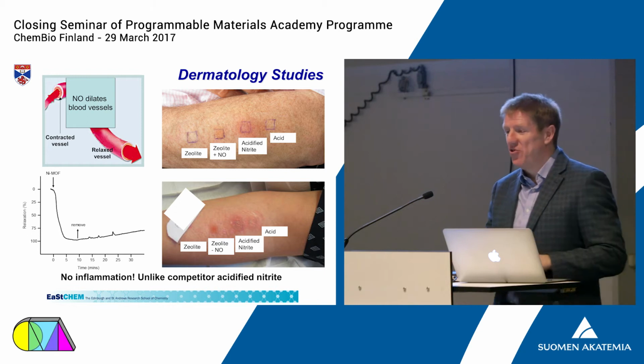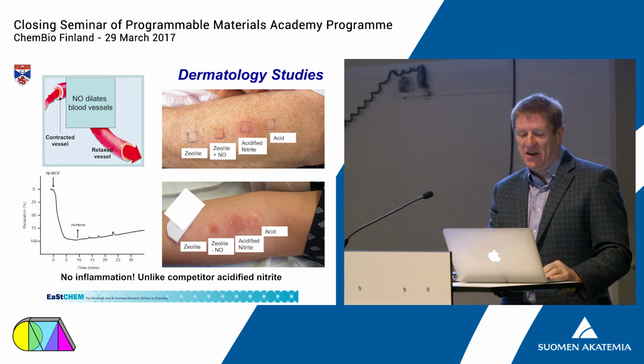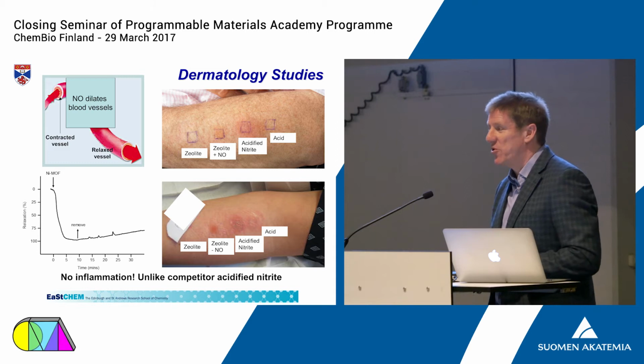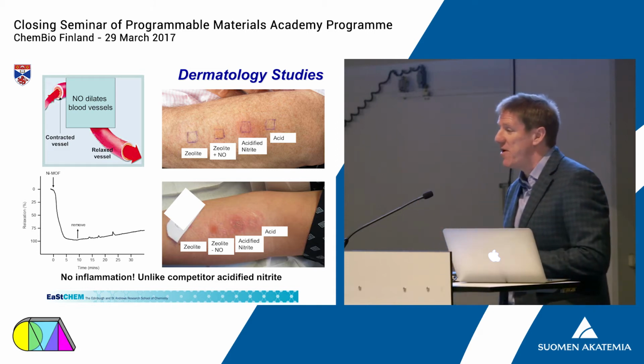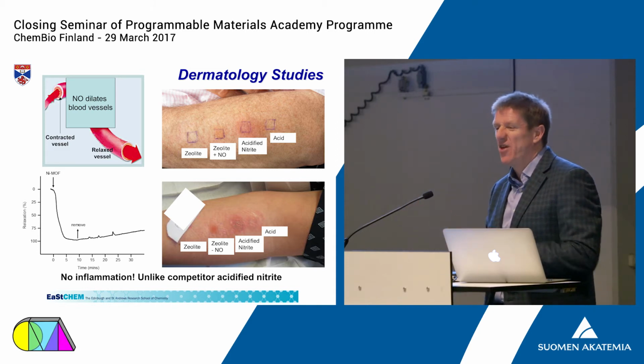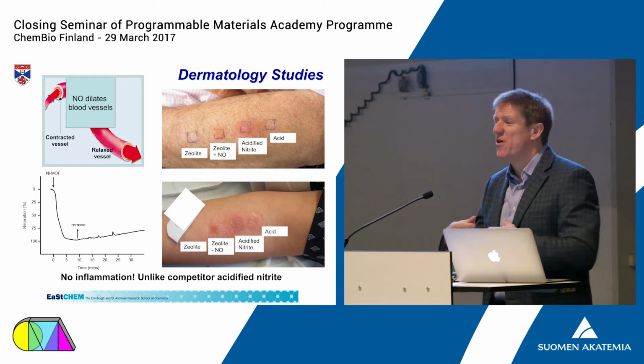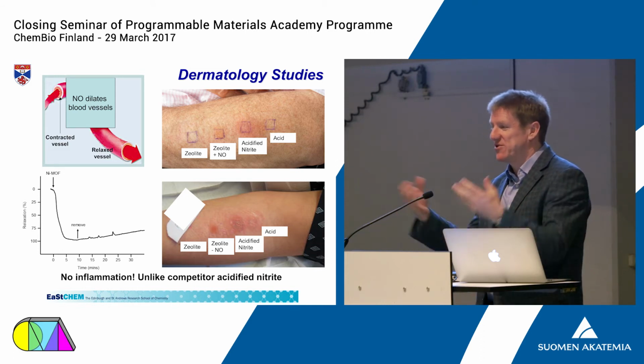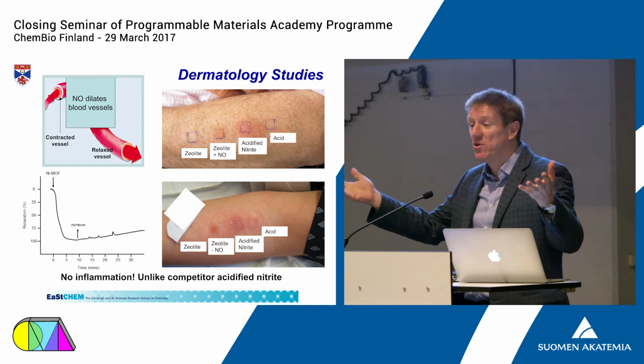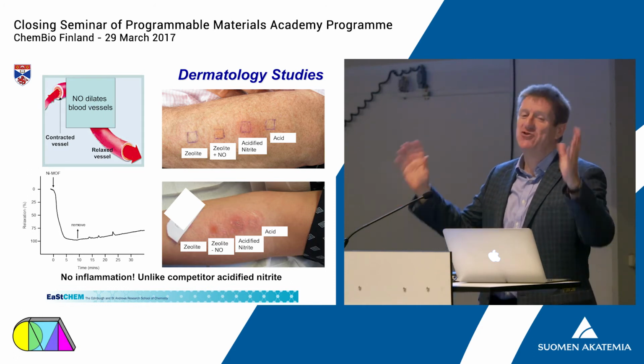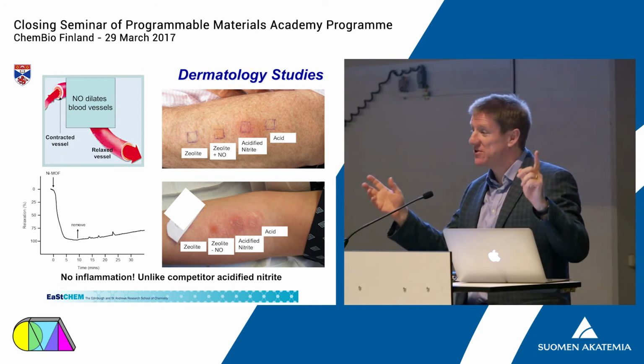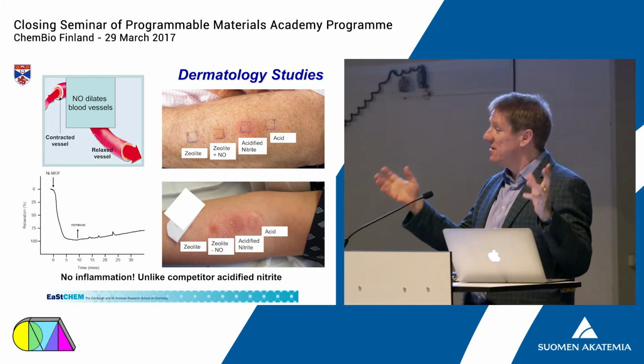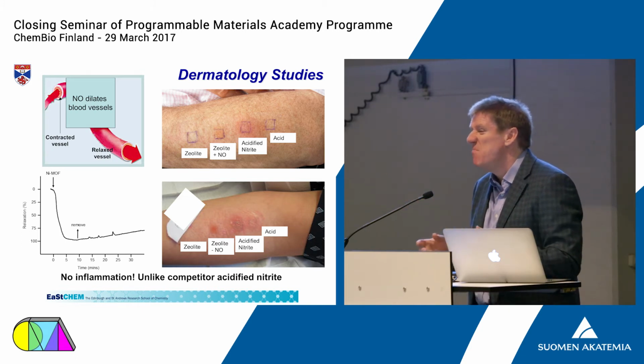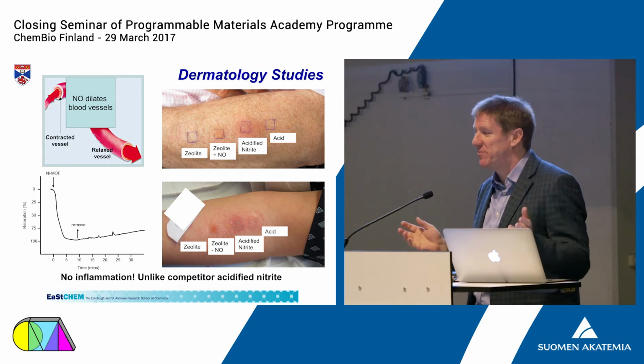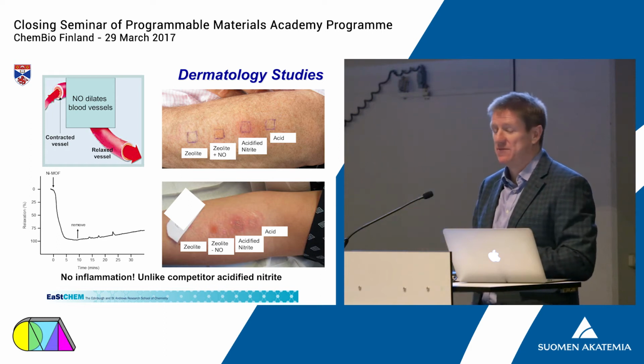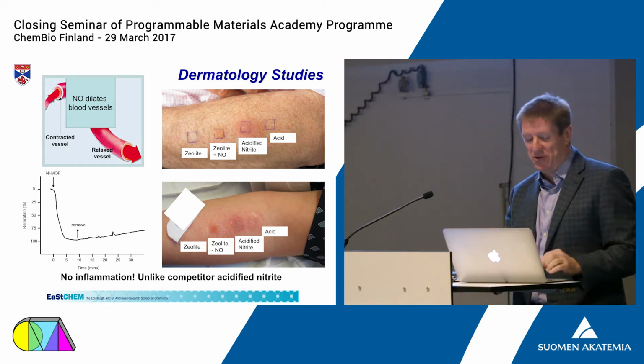So, and you can see that on the skin, in this case, if we just take a zeolite and put it on the skin, or a metal organic framework, we've done both. You put it on the skin, nothing happens really. One of the delights of zeolites in particular is because they're in washing powder, they're all over your skin now, probably. Right? Unless you use liquid powders to wash your clothes. If you use powders, they're all over the skin now. And 99.99% of people have no reaction to zeolites. If you do have a reaction, it's usually to the perfume, to the soap.